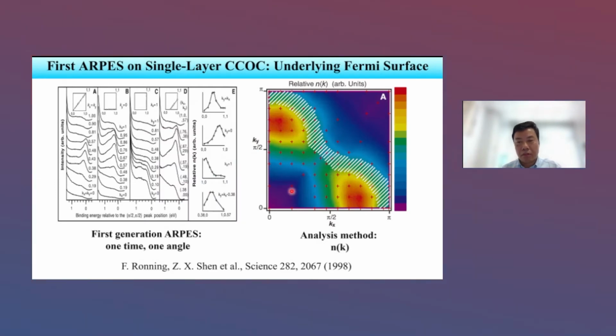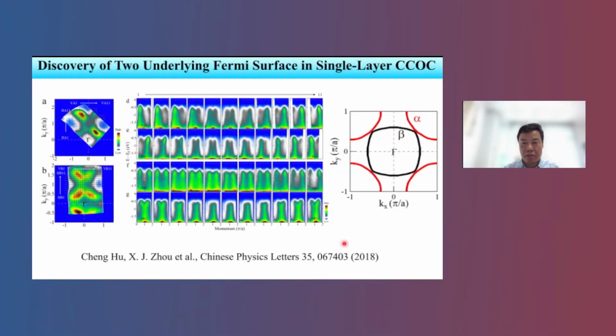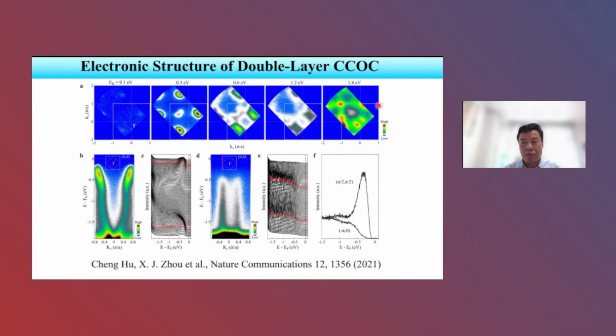So I think a long time ago, 20 years ago, Professor Xingjiang's group already did some pioneering work on studying the electronic structure of the parent compound CCOC. At that time, they identified a so-called underlying Fermi surface, not on the Fermi level, but below the Fermi level. That's 20 years ago. Now, by using some more advanced ARPES systems, we measured this system, and we found that it actually contains two underlying Fermi surfaces. One we call alpha, the other one called beta. And for the double layer CCOC, it's the same as the single layer CCOC, only the states are closer to the Fermi level than the single layer CCOC. So that's why we work on this double layer CCOC.